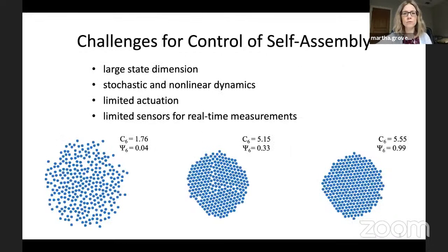So there are a number of challenges for implementing real-time control of self-assembly, and in particular crystallization. There are many atoms or particles, and so there's a large state dimension undergoing stochastic and nonlinear dynamics. Usually we have a limited actuation ability, so we may have a few knobs on our crystallizer, like temperature, evaporation rate, solvent addition, but it's much smaller than the number of particles. And we also have a limited number of sensors for real-time measurement. And so I'll be talking to you about colloidal control, where we actually are watching the assembly under the microscope.